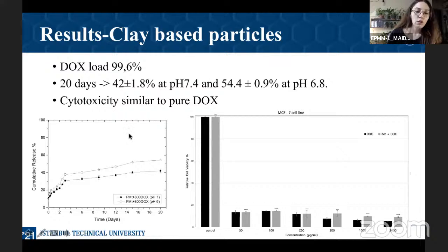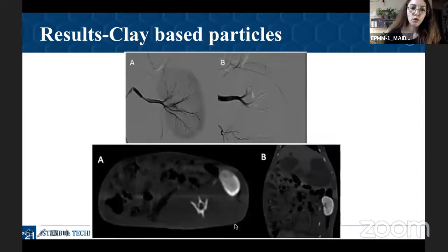When we also look at the drug release behavior, it is also different from magnetic particles. We can see that up to 55% of the drug was released within 20 days, which is a significant difference from the magnetic particles. Here we can see the cell viability of, again, MCF7 cell lines with pure DOX and our clay-based particles. We can see that at all concentrations, clay-based particles perform similarly to pure DOX. Also here, finally, in vivo tests show that clay-based particles were also able to embolize the tumor.